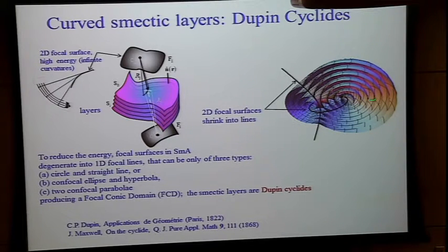equidistant everywhere. You might see this is the Mathematica created image, that the layers are really appearing to be perfectly equidistant everywhere, except, of course, for these 2 disclination lines. But again, these are the lines, and their energy scales as the length of the lines, not as the area of the focal surface that was there previously before I try to find the better energetical solution.